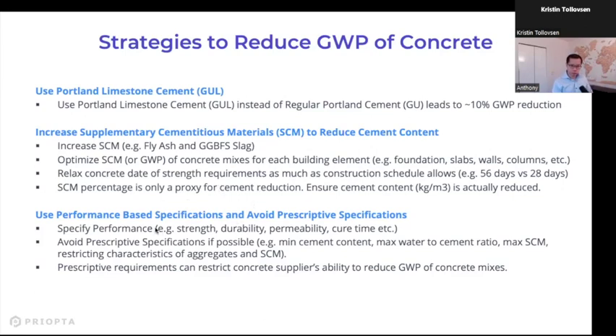And you want to use performance-based specifications and avoid prescriptive specifications. For example, specify performance that you do care about, like strength, durability, permeability, curing time, but avoid some of these prescriptive specifications, which are sometimes in our specs, like minimum cement content, maximum water cement ratio, maximum SCM, et cetera. Sometimes these things can actually restrict what a ready mix supplier can do to reduce the carbon intensity of your concrete mix.